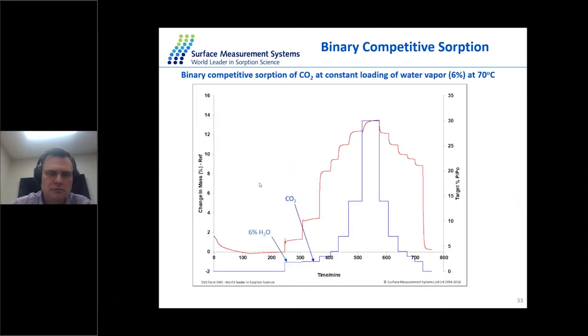Another question, in reference to slide 33: how can you assure the 6% water loading shown in the graph? Is that how you set up the parameters, or did some other change lead to that? So this experiment was done in static mode. In static mode, you have a closed, sealed chamber, so we basically introduce exactly 6% of water before the mass equilibrium. There is going to be 6% of the water in the system, because the water doesn't have to go anywhere. When the mass equilibrium is reached with the sample, we calculate the adsorption capacity in millimole per gram. This is the capacity for the water vapor, and the relative humidity was 6%. The short answer is that because it's static mode, we assure there's going to be 6% of water vapor.